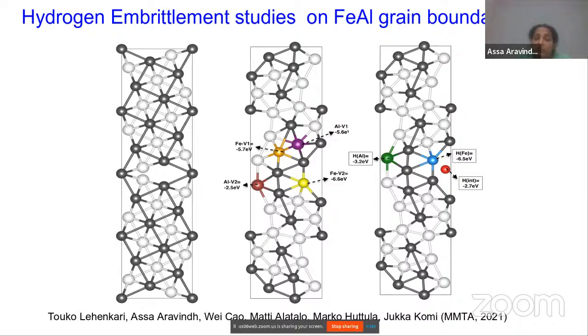For example, there are already structural defects in the material called grain boundaries. So this hydrogen can go and stay there more easily than in the bulk of the material. So in this study, we have checked. This is a grain boundary of FeAl without any defects. Then we introduced these defects, hydrogen, in many positions, and then calculated the formation energy and successfully explained the energy formation mechanisms here. This is actually the work of a bachelor thesis, and the student published a paper out of it. Very interesting, very simple but very powerful study.